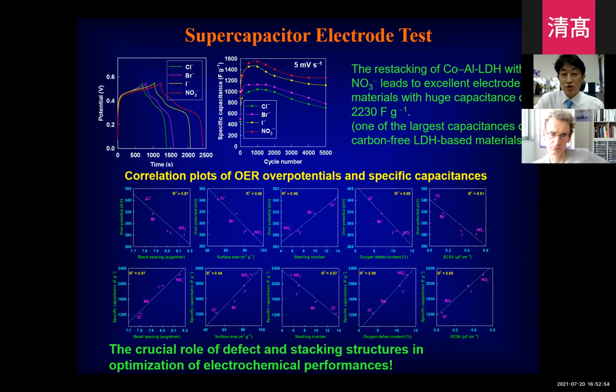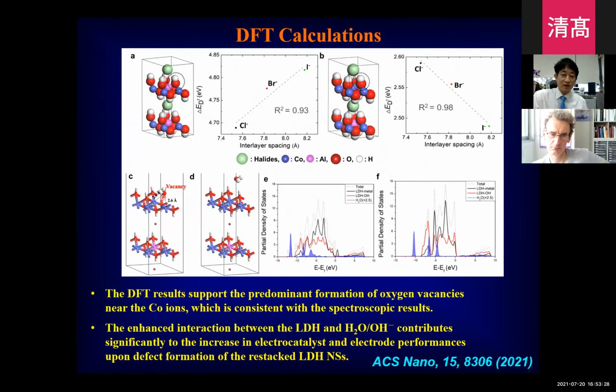Also, we applied those materials as a supercapacitor electrode. As you can see here, the reassembling with the nitrate ion is also valuable to enhance the electrode performance of the LDH nanosheet. Actually, it's one of the best electrode performances of carbon-free LDH-based material. From the correlation plot, we confirmed the crucial role of defect and stacking structure of the LDH in optimizing the electrocatalyst and electrode performance of the LDH material. From the defect calculation, we confirmed the increase of the interlayer space leads to the increase of defect level, and the generated defect site can act as an electrocatalytically active site to enhance the OER catalytic activity.